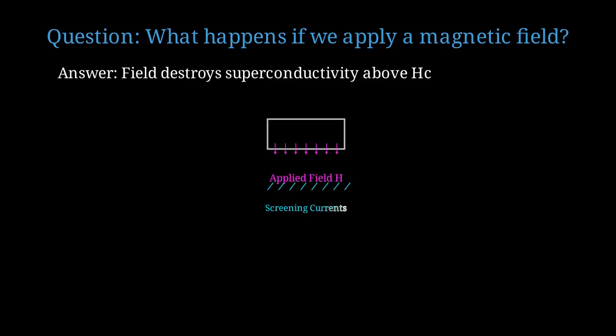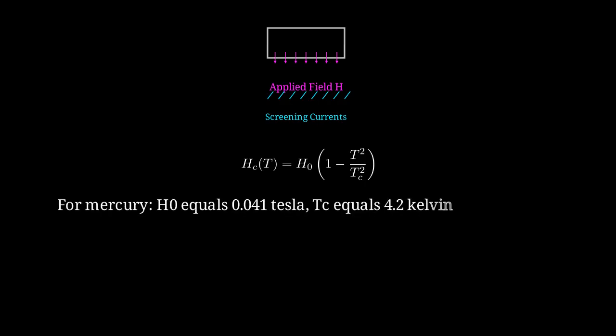When we apply a weak magnetic field to a superconductor, screening currents flow on the surface that perfectly cancel the field inside the bulk. This is the Meissner effect. But these screening currents cost energy. The critical field depends on temperature. Near T_C, it follows approximately H_C(T) = H_0 (1 − T²/T_C²). Here, H_0 is the critical field at 0 temperature. For mercury, H_0 is approximately 0.041 Tesla, and T_C is 4.2 Kelvin.